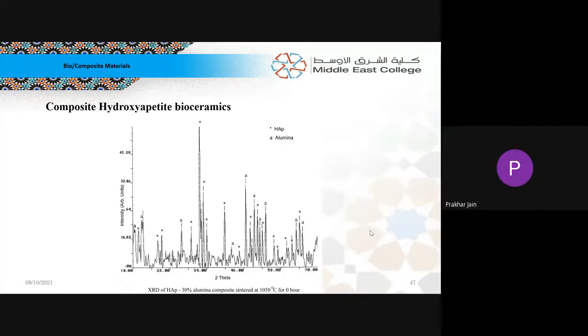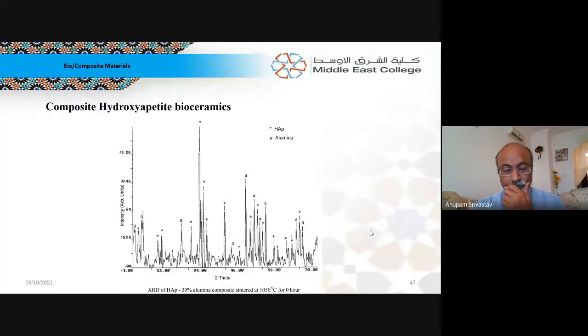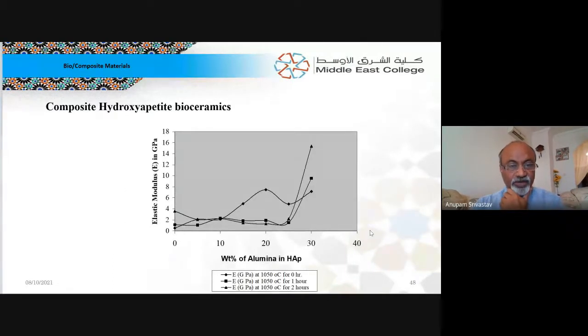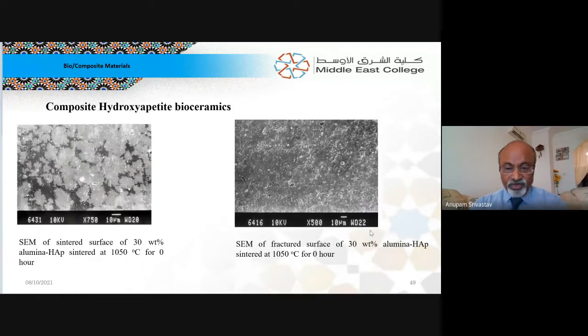And then we characterize the hydroxyapatite for mechanical strength. We see the internal structures using electron microscopy. We have to see how strong or how dense the structures are that are formed. As you can see on the right-hand side, there are some micropores visible. These are the pores that, when subjected to tensile stresses, join together and make the material fail by a brittle failure mechanism.